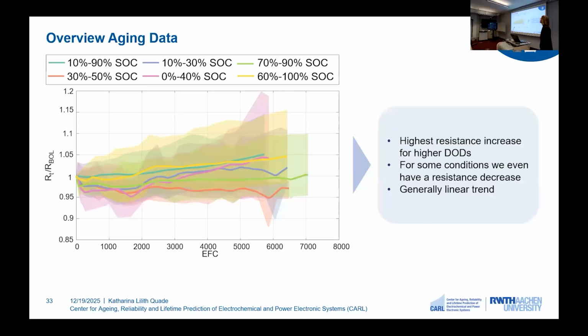However, we see a different trend. We see that the highest resistance increase is for higher depth of discharges, and for some conditions, especially for the orange condition, we even see a resistance decrease. Generally, we have a linear trend. So, to summarize, we can see that for the different conditions, we have very different aging behavior measured with the help of the capacity and also the resistance. And even within the same condition, we have experienced different aging behavior.